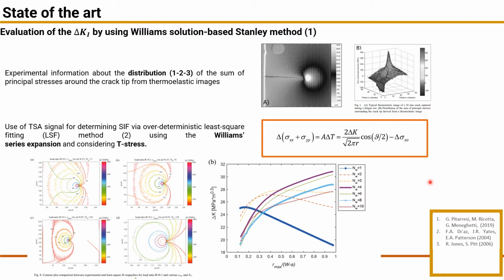All these works are based on the classical theory of TSA, in which temperature change is related to the stress change through the thermoelastic constant for an isotropic material under linear elastic and local adiabatic conditions. But this classic approach is only valid if the change in the mechanical properties of the material with temperature can be considered negligible. Moreover, depending on the material, the problem of the mean stress influence was also not addressed.